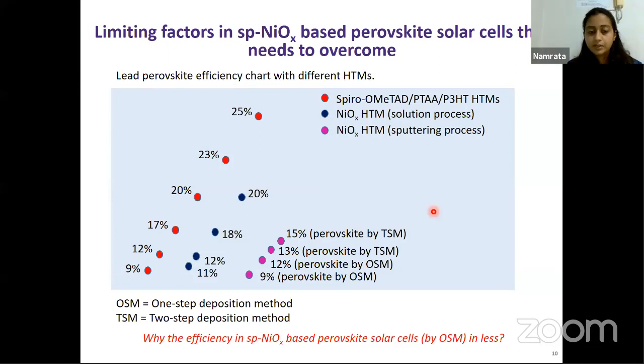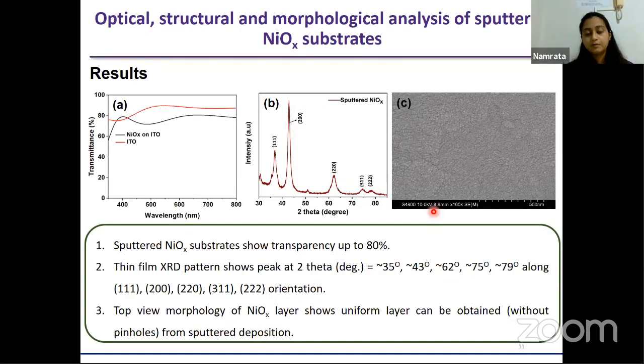To understand that, we carried out a series of investigations, and to begin with, we sputtered nickel oxide with optimized conditions. We obtained highly transparent nickel oxide with a transmittance of nearly 80% in the visible region. From the XRD and the SEM image, we could confirm that we had obtained a uniform nickel oxide structure.